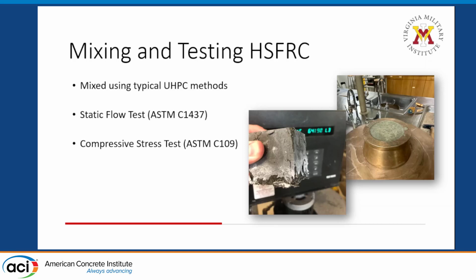completed with respect to ASTM C109. For the stress test, 2 cubes were tested at 3, 7, and 28 days after a wet cure with water and saturated lime, and each mix had 3 batches, so essentially there was 6 trials for each cube.